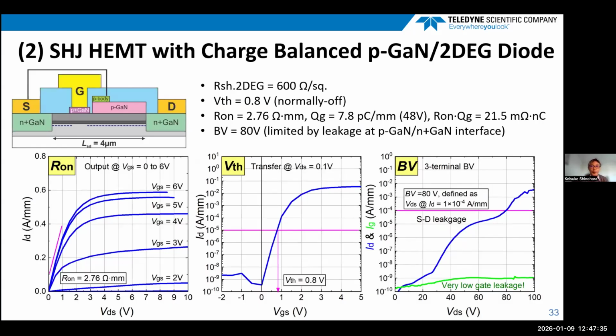So here I show the super heterojunction result, and it shows a very good pinch-off operation with the normally-off condition. The R-on of this device is 2.76 ohm millimeter, and the threshold voltage is 0.8 volt. The breakdown voltage of this device was 80 volt, which is limited by the drain leakage current, even though the drain leakage current is very low. So we are working on this to further reduce the gate to drain to source leakage current in order to improve the overall breakdown voltage. However, this device shows a very small gate charge because of this PN junction, and a QG of around 21.5 nanocoulomb was obtained.